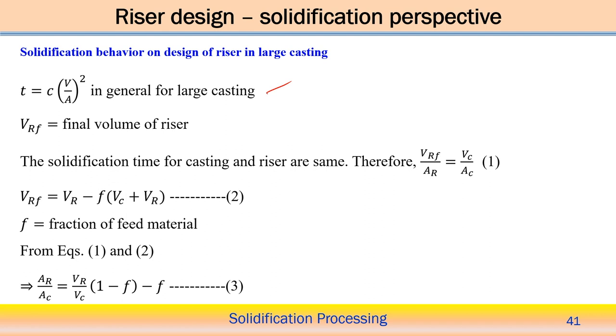process. So we are assuming first that the solidification time depends on the square of the volume by area ratio. Now suppose VRF is the final volume of the riser required in this case. Since the solidification times of the casting and the riser are the same, the riser should solidify after the casting, but mathematically we can assume that if the solidification time for the casting and riser are the same, then the V by area ratio for the riser should be equal to the V by area ratio for the casting.